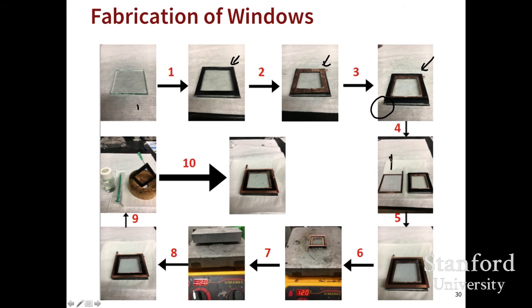Then we have a second piece of glass that has the ITO on it, and it has copper tape around the edges to help spread the current. So we'll be bringing current in from all around the edge of the device. And in step 5 here, we've sandwiched all of that together. And then we're putting it on a hot plate at 120 degrees C. We put some weight on top of that, and that presses the two pieces of glass together, and the rubber is a little bit softened up, and we get a nice seal between the two pieces of glass.